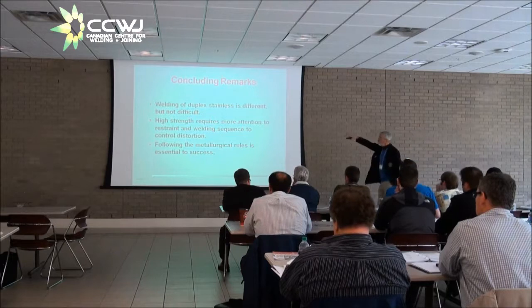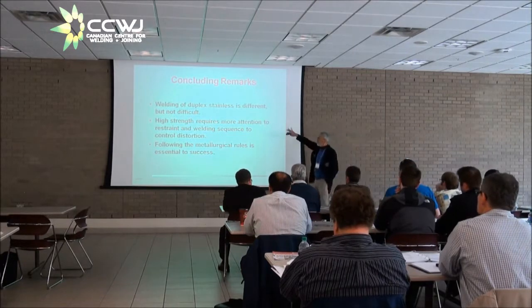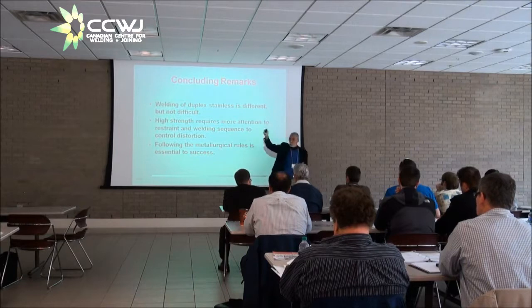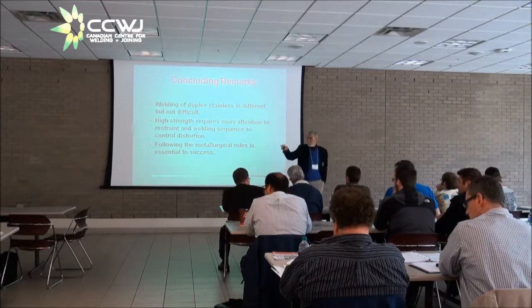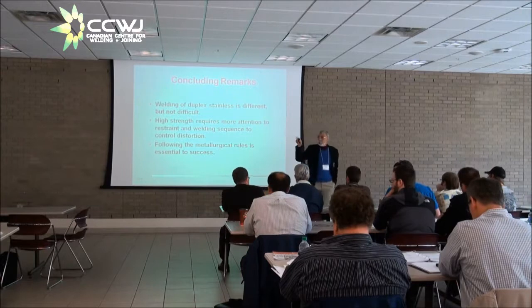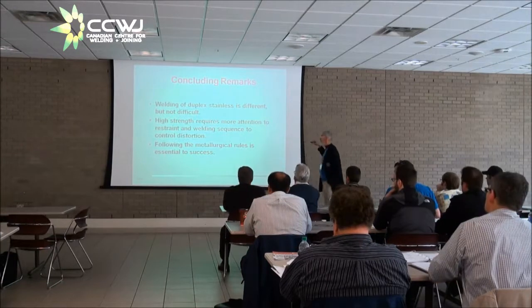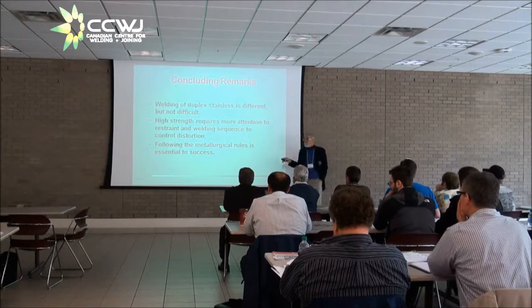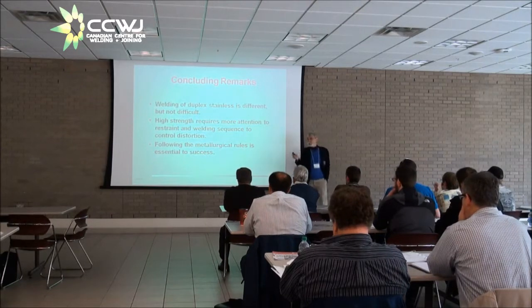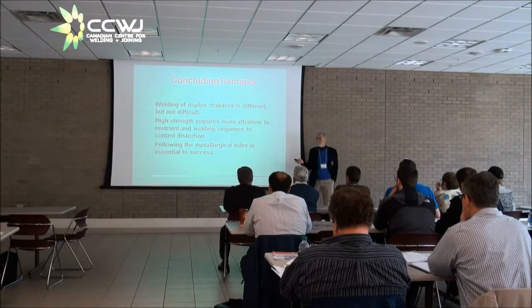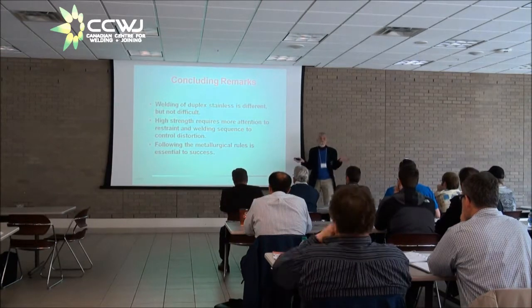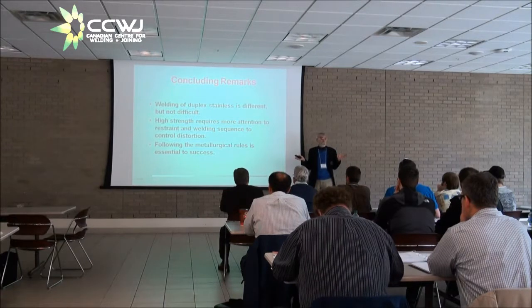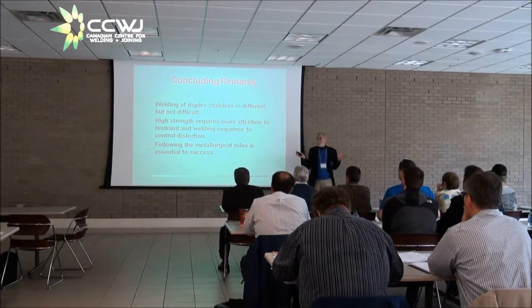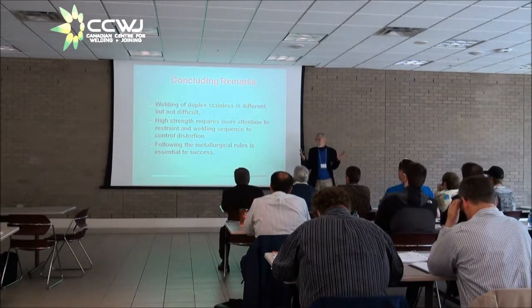Now, I would disagree with one thing that was said this morning about distortion. I think, Julia, you said it? Okay. And I think maybe Ellen said it too, that you get less distortion with duplex. Well, that depends. One of the things you have to appreciate is that duplex is a whole lot stronger than austenitic. If you allow it to move freely, austenitic stainless will move more than duplex. But if you do a half-assed job of restraint, duplex will move more than austenitic.